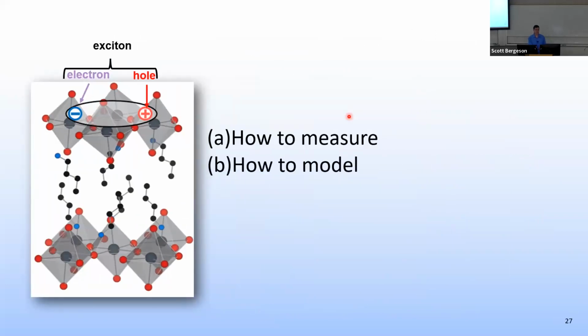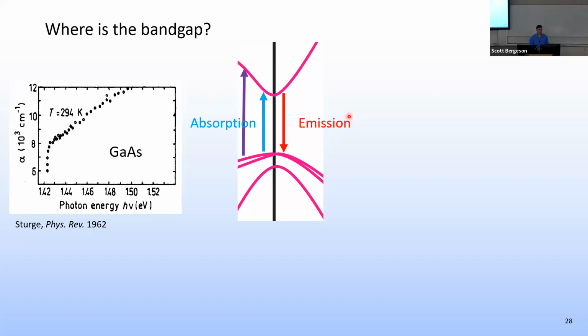So we want to study the properties of these excitons. It's very important. We want to measure them, we want to model them, and by measuring and modeling, we can hopefully improve the ability to design materials to have the desired properties that you want. So typically, to measure the band gap, back in the 1960s, you might measure the optical absorption. And as I mentioned before, the absorption starts when the photon has at least as much energy as the band gap. If you have photons with more energy, they're also absorbed. And so you get some sort of plot like this, where absorption is increasing and increasing, but the place where the absorption starts, that's the band gap. So that allows you to identify the band gap.